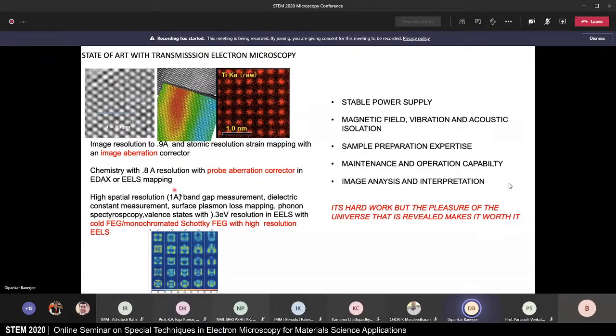We can combine that with atom probe tomography, an area that I have not touched upon in this talk, but just to point out that electron energy loss spectroscopy combined with the focused probe that is available with today's instrumentation allows angstrom spatial resolution, band gap measurement, dielectric constants, surface plasmon loss, and a variety of valence states. All of this requires something that Kamanyo touched upon. Okay, it's hard work, but the pleasure of the universe that is revealed makes it worth it. And I must emphasize what Sri Kumar pointed out, that the combination of these techniques with techniques that are used at different length scales, such as synchrotron diffraction, for example, leads us much better to a total understanding of the system. Thank you very much.